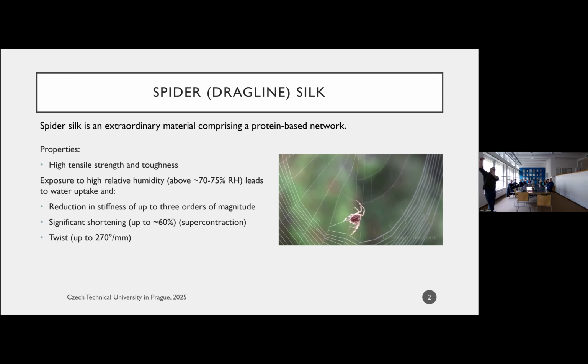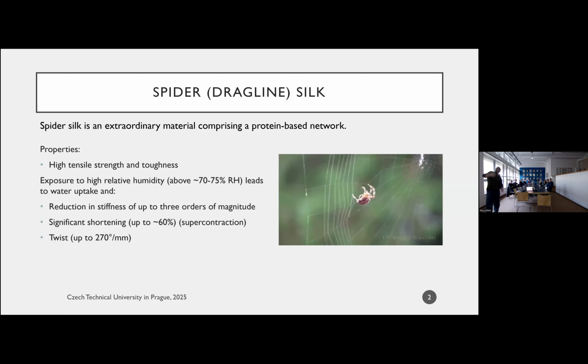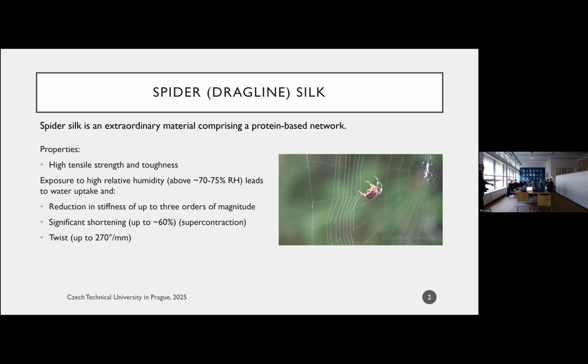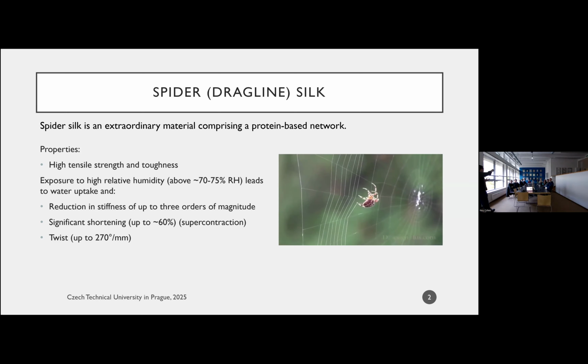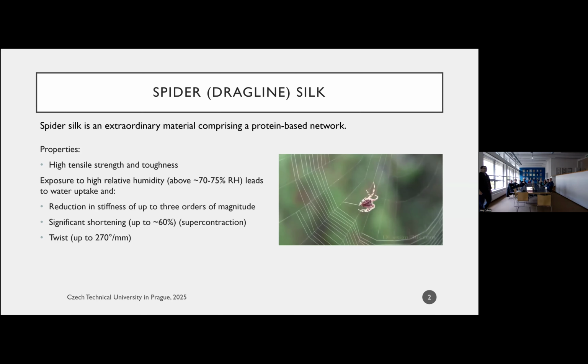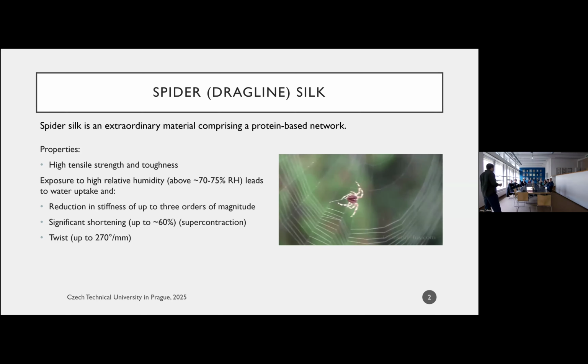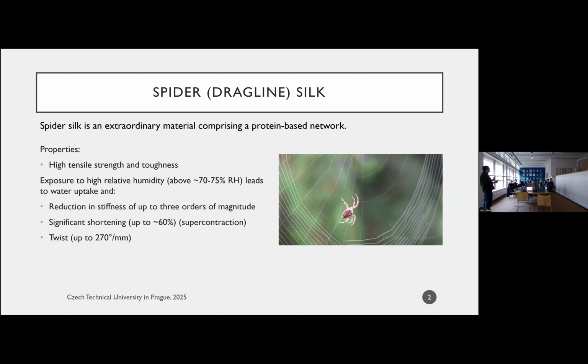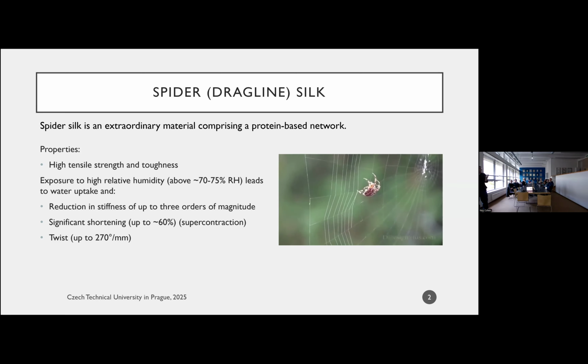If we take these silk fibers and we subject them to regions of high humidity, it turns out that we're going to see 3 phenomena that are extremely counterintuitive, especially if you've worked on gels. So if we take one of these fibers and place it in an environment with very high humidity, above 70-75% relative humidity, the first thing we're going to see is that the fiber softens by 2 to 3 orders of magnitude in response to a relatively moderate water uptake. This fiber has a water content of about 20% in its fully swollen state, and it responds by decreasing its stiffness by up to 3 orders of magnitude. That's pretty incredible. That doesn't happen in every material.